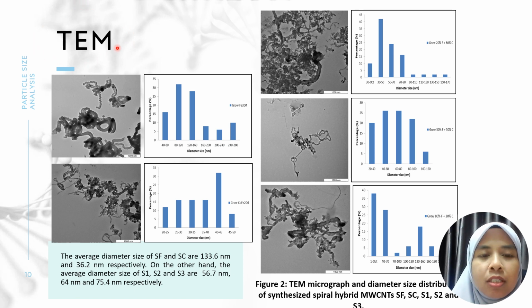So this is the TEM result for various samples. So the average diameter size of SF and SC are 133.6 nanometer and 36.2 nanometer respectively. On the other hand, the average diameter size of S1, S2, and S3 are 56.7 nanometer, 64 nanometer and 75.4 nanometer respectively.